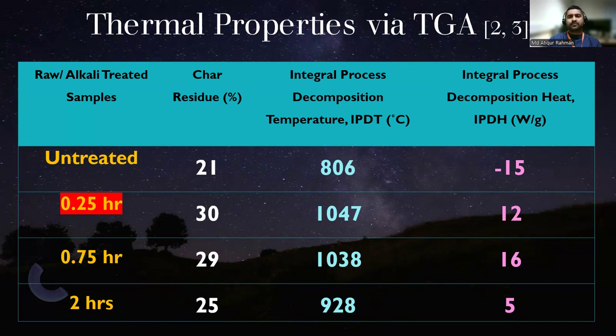At 2 hours, it actually deteriorated. You can see that is perhaps one of the reasons, because of the prolonged time, some of the cellulose has been deteriorated. And if you see the IPDT, that is the integral procedure decomposition temperature, this is another way to represent the thermal stability. This one was introduced by Doyle.